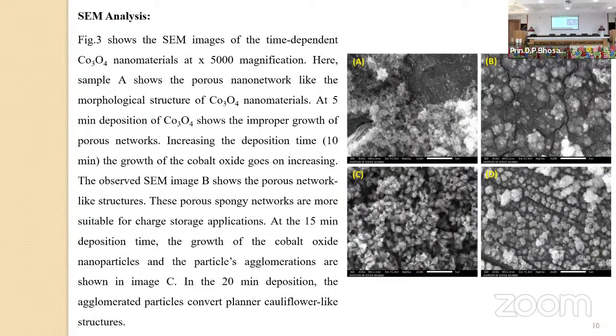Okay, next. Then another physical characterization, that is scanning electron microscopy, which shows the different morphologies of the deposited surface. A shows the 5-minute, B shows the 10-minute, C shows the 15-minute, and D shows the 20-minute deposition time. It shows some porous networks, some interconnected networks, and a spongy network. But here we see from the result of the analysis that the 10-minute deposition gives the porous network of cobalt oxide, which is more applicable for supercapacitor application.